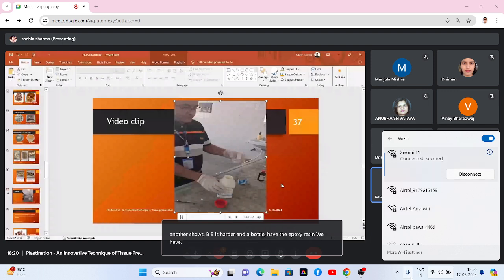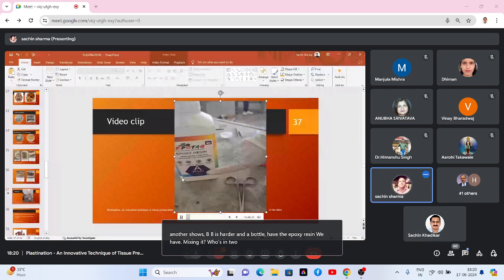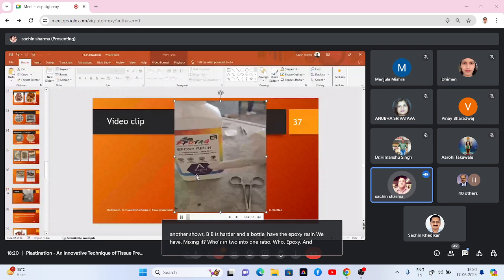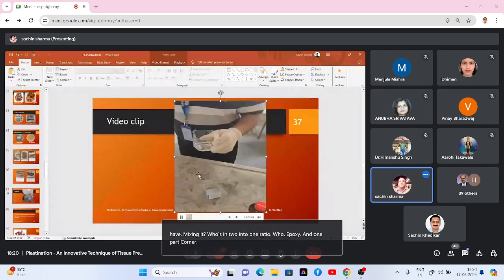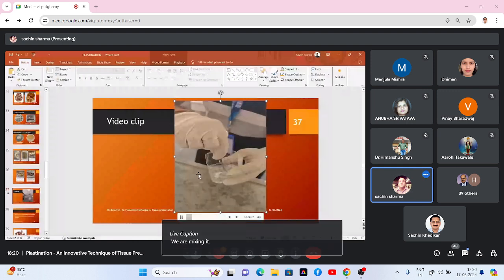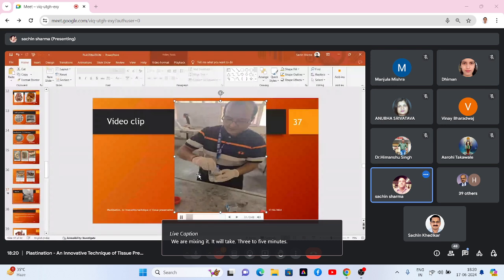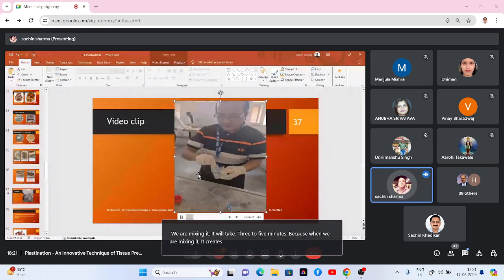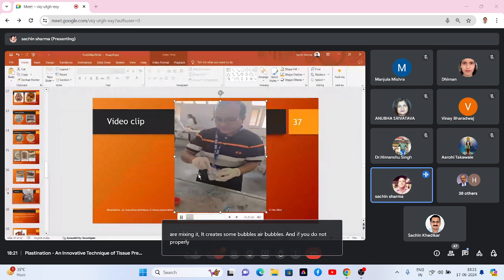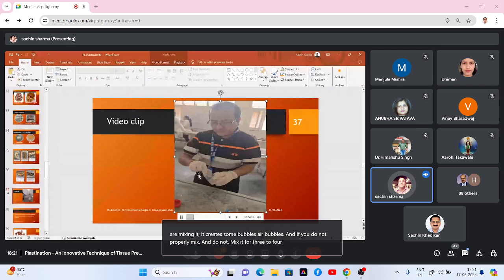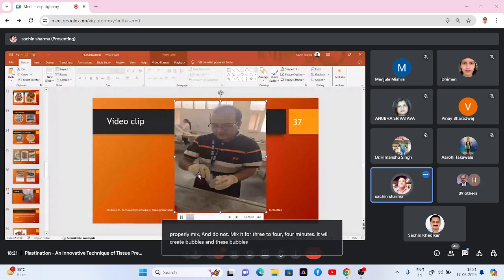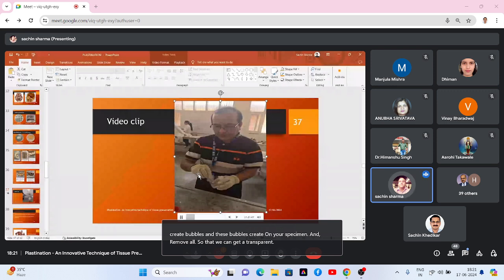We are mixing it in a 2:1 ratio, 2 parts epoxy and 1 part hardener. It will take 3 to 5 minutes because when we are mixing it, it creates air bubbles. If we do not mix it properly for 3 to 4 minutes, it will create bubbles, and these bubbles create a false appearance on your specimen. So mix properly and remove all bubbles so that we can get a transparent, clear specimen. So this is the mixing process.